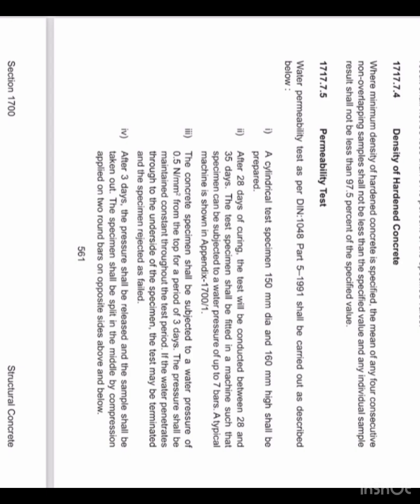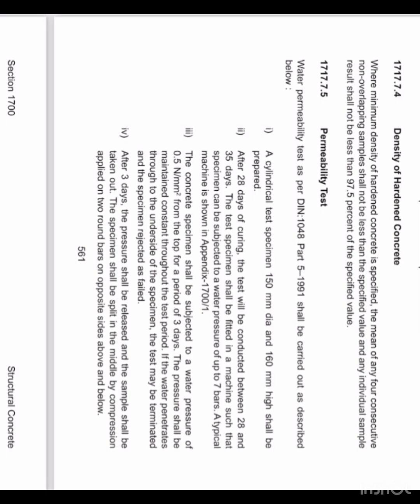Permeability test. Water permeability test as per DIN 1048 Part 5, 1991 shall be carried out as described below. A cylindrical test specimen 150 mm dia and 160 mm high shall be prepared after 28 days of curing. The test shall be conducted between 28 and 35 days. The test specimen shall be fitted in a machine such that the specimen can be subjected to a water pressure of up to 7 bar. A typical machine is shown in Appendix